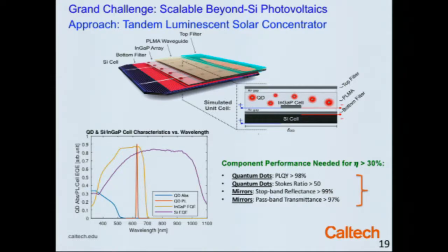So we're interested, of course, in making photovoltaic modules that can exceed the 30% efficiency range. So we need to have quantum dots that are highly luminescent. The Stokes ratio, which is the ratio of absorption to emission at this luminescence wavelength, should be a factor of 50. That's just a matter of how well you can engineer the ensemble absorption of quantum dots.